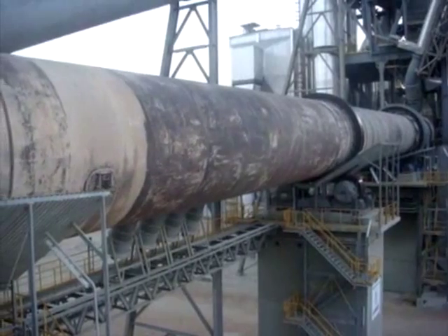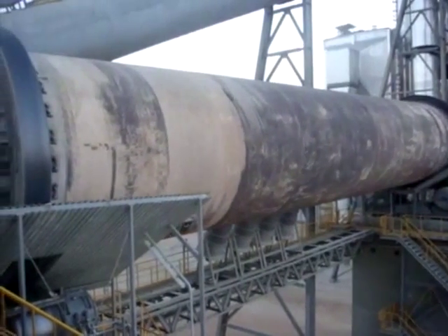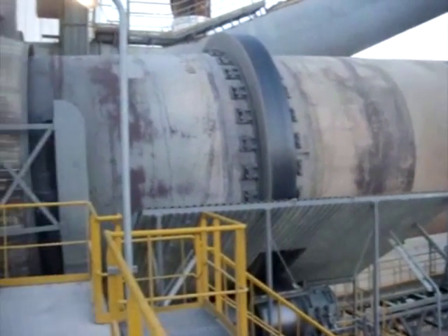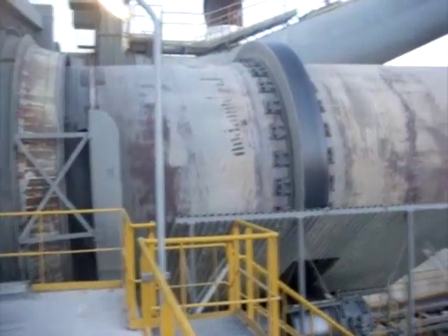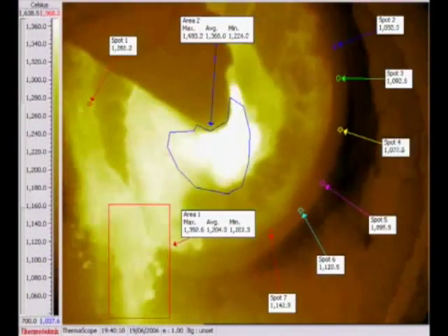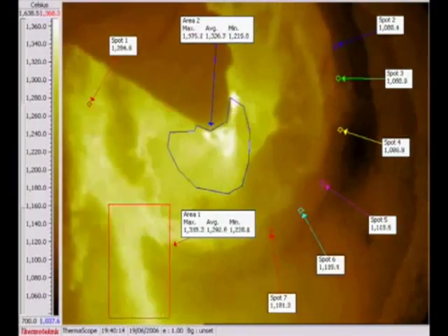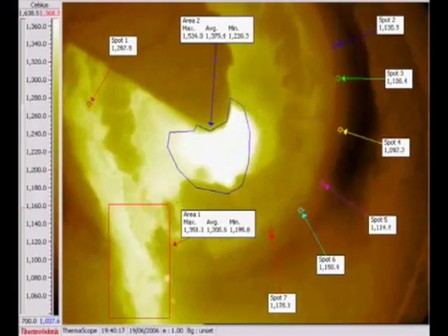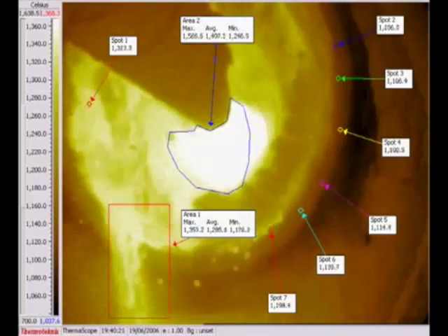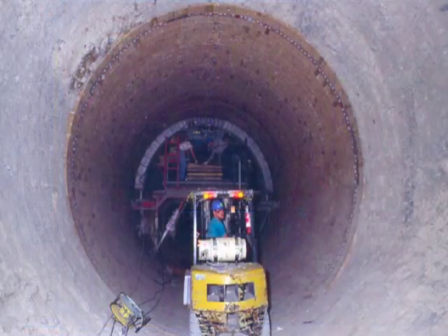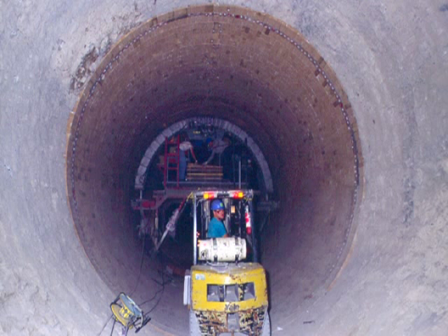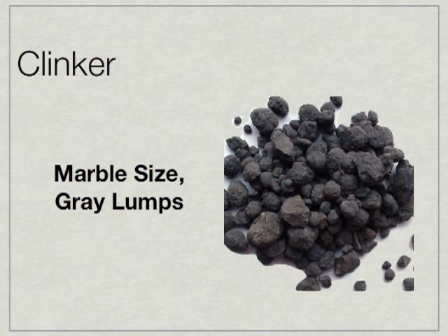From there, the material is fed into the kiln. The kiln is set at an angle so that it is a continuous process. A kiln will turn about two revolutions per minute, slowly moving the material through. Inside the kiln it can get extremely hot. This time lapse shows the temperatures at various locations, and up top you can see the average temperature in Celsius inside the kiln. Once the kiln hits about 1500 degrees Celsius, the powder begins to fuse itself together and forms what is known as clinker — marble-sized gray lumps that come out the other end of the kiln.